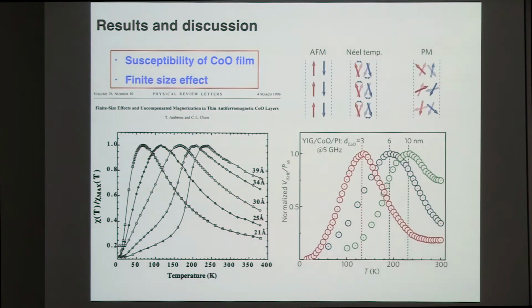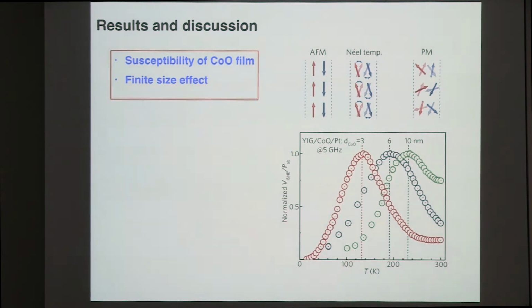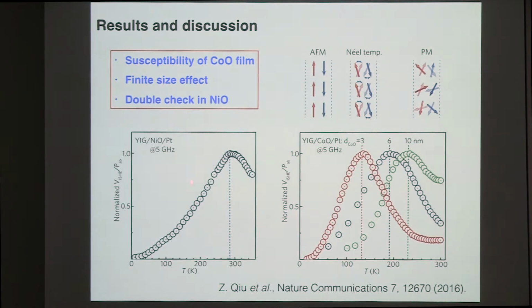So we prepared different thicknesses of cobalt oxide (CoO), and we see that this peak position does shift to high temperature when we increase the thickness of cobalt oxide (CoO). So maybe it indicates something. Maybe it's really the Néel temperature. We also continued to look at this behavior in a structure where we put nickel oxide instead of cobalt oxide (CoO). So basically, this behavior looks pretty universal, at least for these two systems.